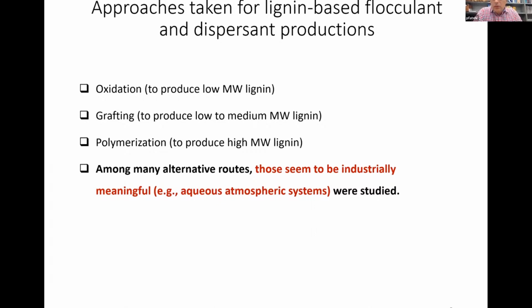Grafting is exactly the opposite. We are not, let's say, degrading lignin. We are adding groups. We are decorating lignin, adding functional groups to it. Again, you can produce low to medium molecular weight. Medium molecular weight means a molecular weight of around 50,000, 60,000. But the yield is more than 100% because we are adding things to lignin.